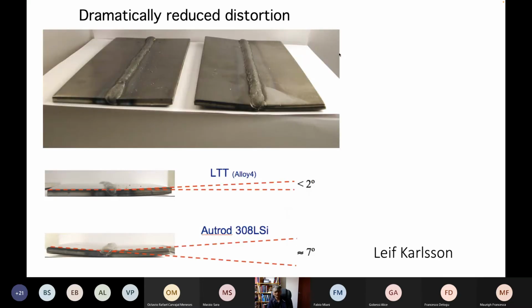And residual stress has two effects. One is that you have a locked-in stress system, which reduces your design parameters. But the second is that you can get ugly distortion of your welded component. So here, for example, you can see that these plates, which were originally lying flat on the surface, after welding, they've developed a distortion with an angle between these two. And if you use a welding material which remains fully austenitic up to room temperature, then you get a large distortion. By using this low temperature transforming alloy, you dramatically reduce the distortion and therefore also the residual stresses if this component was large. So I'll finish the lecture there.